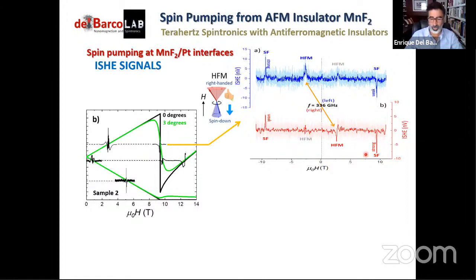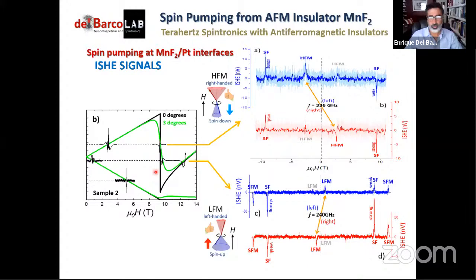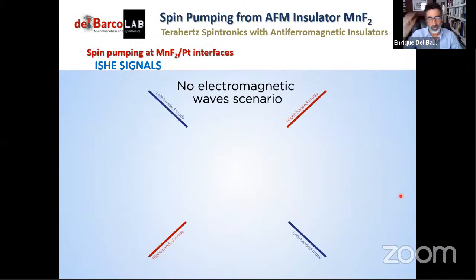We go to low frequency, 240 gigahertz, and we do the same analysis, and we see similar things, but now the low frequency mode behaves exactly opposite to the high frequency mode. So you see, for right-handed circularly polarized microwaves, we don't see a feature at positive fields. When we saw a feature for the high frequency mode, that appears when we reverse the polarization of the microwave. So it's just basically the opposite two effects. That is indeed what we expect, because these two antiferromagnetic modes are of different chirality. And we just expect to excite them only when you hit the mode with the same chirality with your microwaves. All right, so I have a little animation here to explain this better.